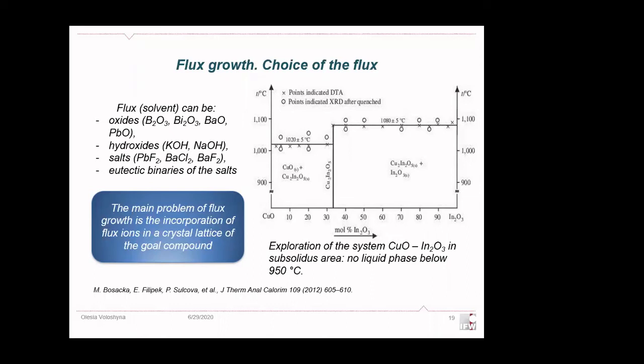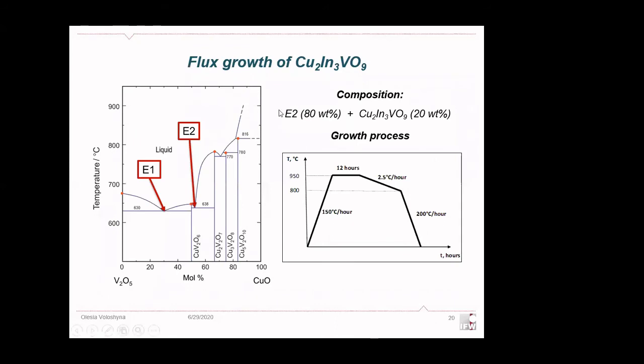So this is a eutectic binary between oxides included in our system. And as you can see from the binary system for copper oxide and indium oxide, below the temperature of 950 degrees, no liquid phase was determined. And interestingly, in the binary system between copper oxide and vanadium oxide, we obtain two different eutectics that are quite good for use as a self-flux. And we use in our experiments eutectic 2 as a self-flux.